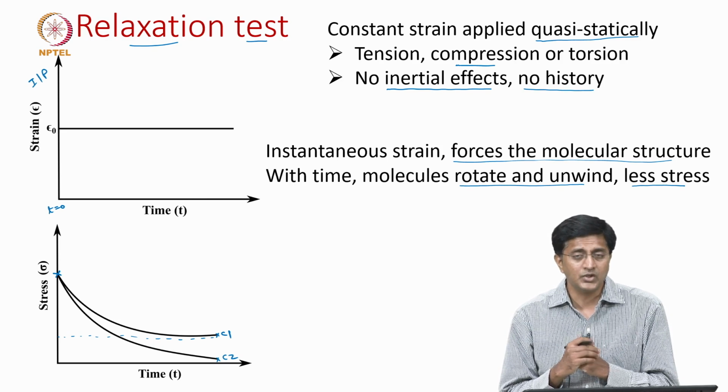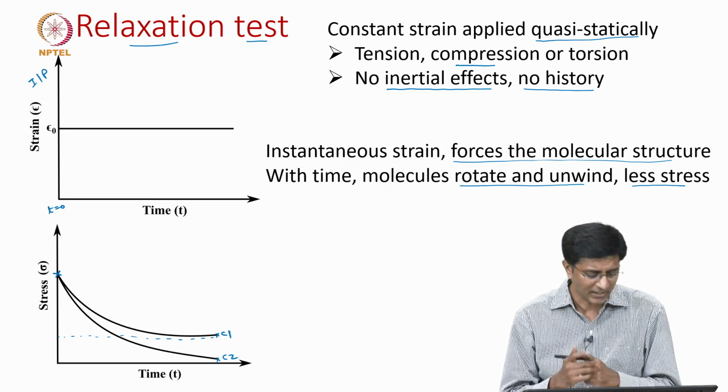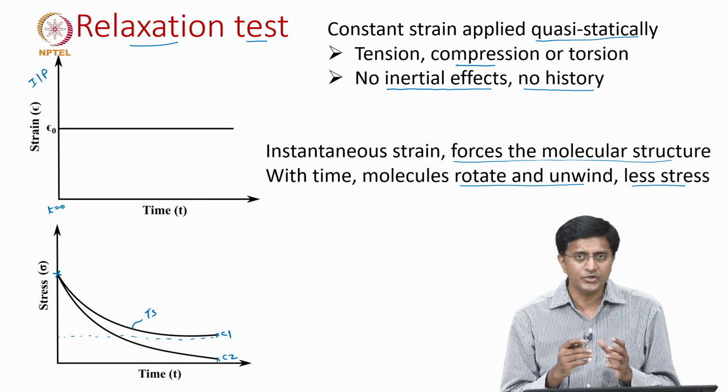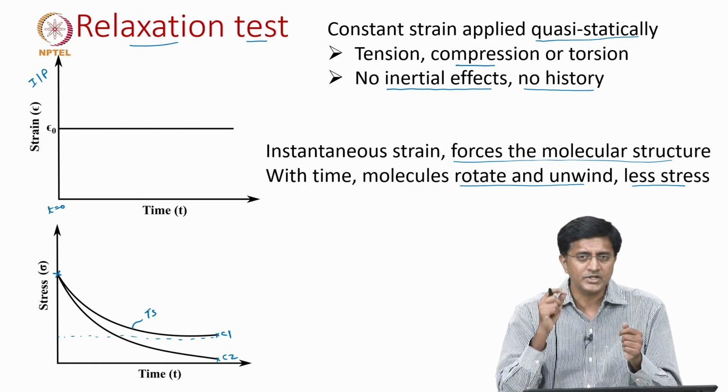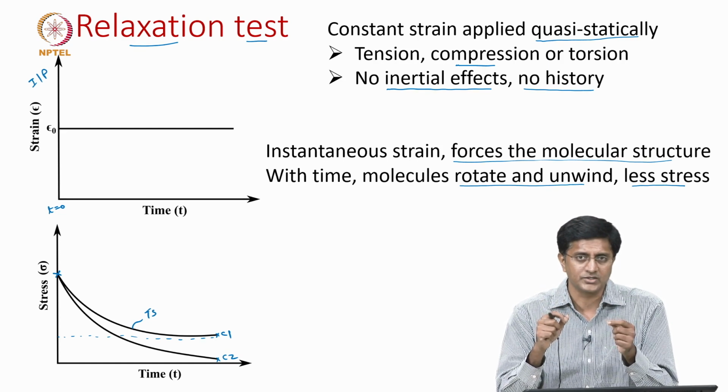Right. So, let us start with thermosets. Which of these curves will it take? The answer is, thermosets will go to a constant position, because thermosets, as we know, are networked polymers, meaning there are cross links.